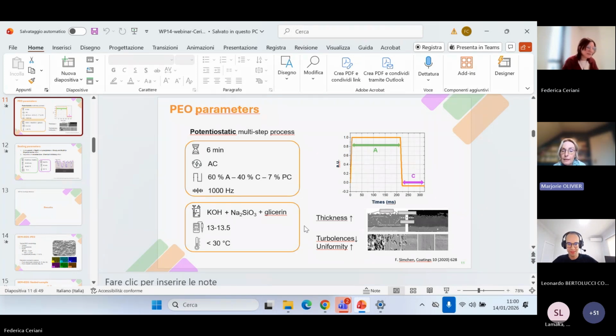And last one, I suggest, would it be better to use two-step sealing to avoid precipitation in the bulk? First bath zinc nitrate, second alkaline to promote only precipitation in the pores. Oh, okay. It's a good suggestion. Thank you. Good suggestion.